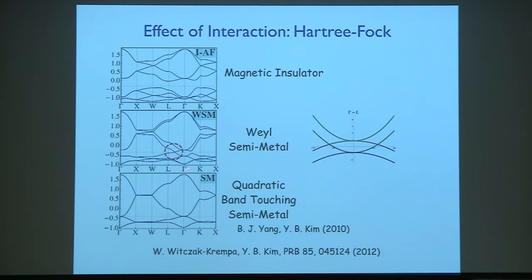You see, the reason why here you get a time-reversal-symmetry-breaking Weyl semimetal is that you actually enter the magnetically ordered state. In semiconductor systems, you don't have a magnetic order. So the easiest way to generate Weyl fermions is actually to break the inversion symmetry, not the time-reversal symmetry. But here we are doing something different. We are not breaking inversion symmetry. This magnetic order doesn't break any lattice symmetry, remember? It only breaks time-reversal. So in a way, this is slightly different from all other Weyl semimetals that have already been discovered. But nonetheless, this is what is supposed to happen.